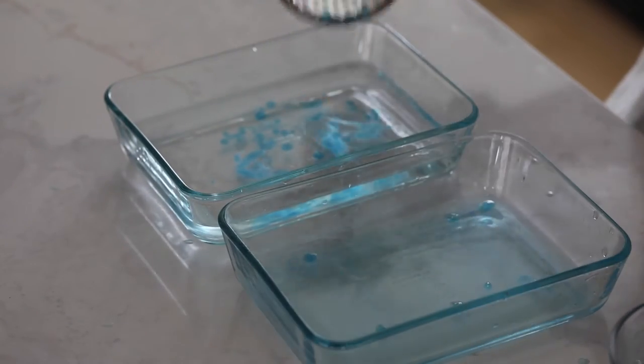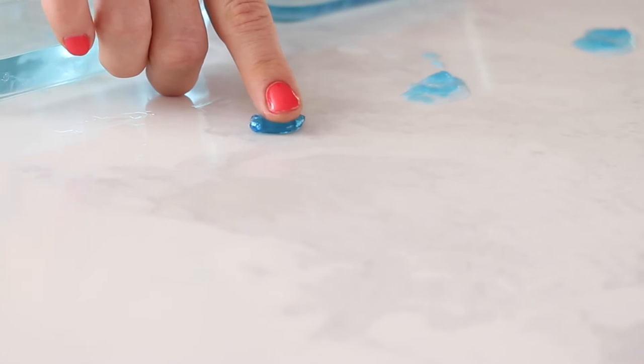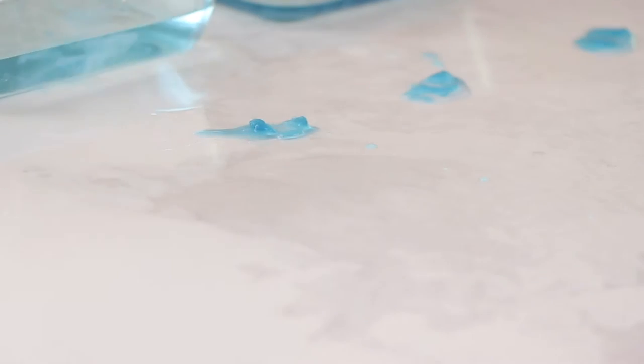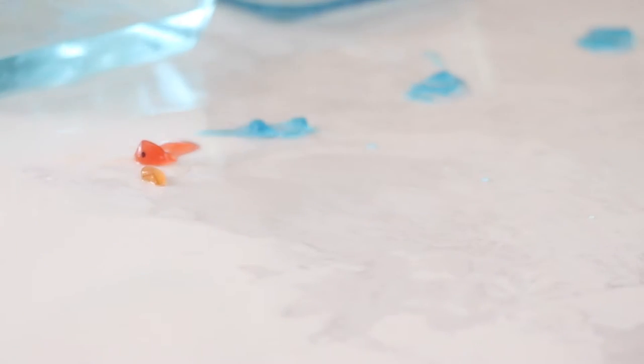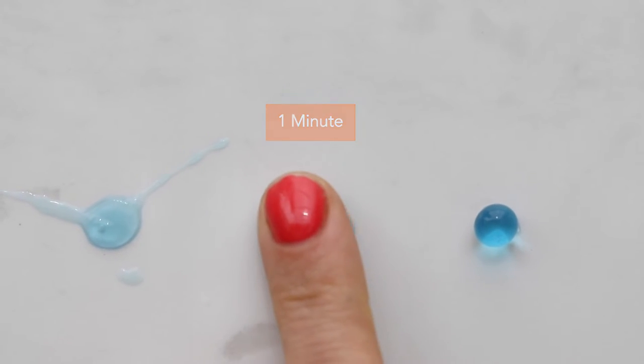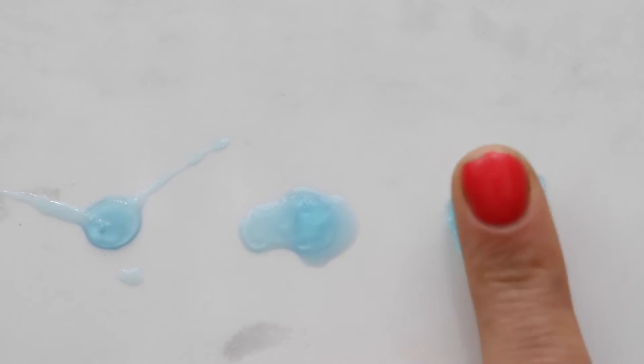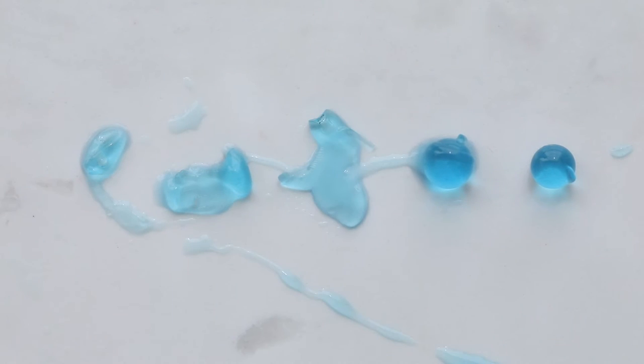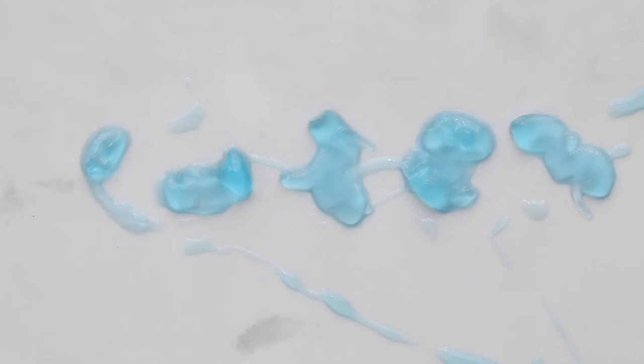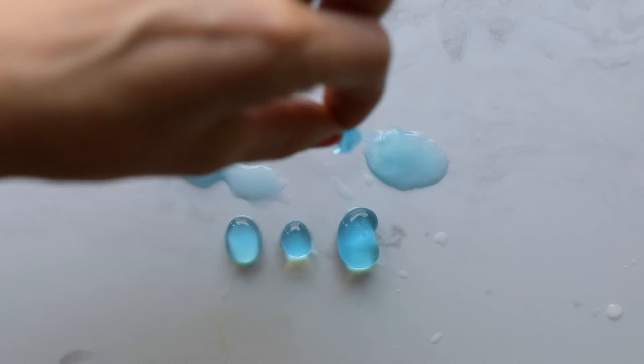The other key piece is texture, and that all has to do with how long the spheres sit in the calcium chloride bath. We did a bunch of tests letting the spheres sit for different amounts of time. Ultimately, we found that about a minute was best, but it did depend on the size of the sphere. One that sat for about three minutes took a lot of force to break the outer coating and there wasn't much liquid on the inside, while the store-bought boba didn't require much force and had a lot of liquid. Looking at this more methodically, comparing 30 seconds, one minute, and three minutes, you can see a big difference in the gel-to-liquid ratio. To learn more about texture, we talked to food scientist Tessa Porter, who designs candies at her company Sprink. After talking to her, we realized it was essential to have a really thin outer coating that quickly popped.